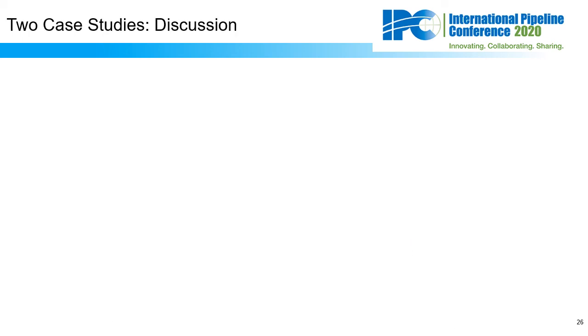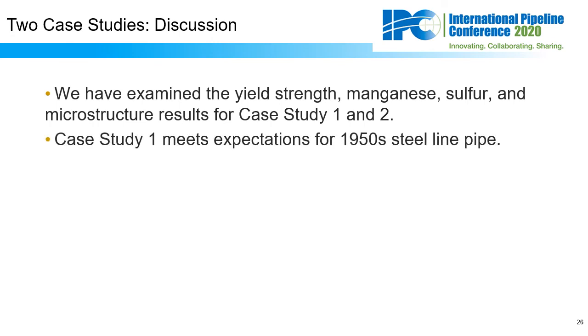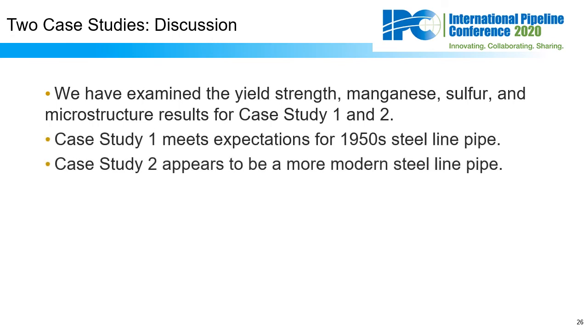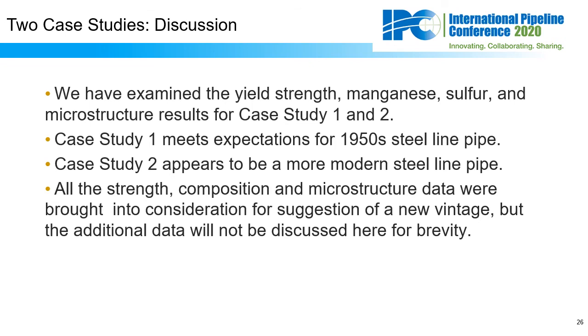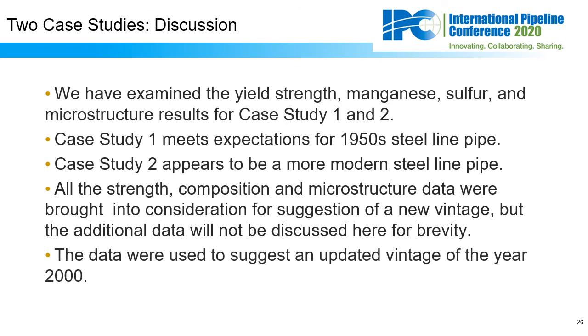So now that we've looked at the yield strength, manganese, sulfur, and the microstructure, our next step is to suggest a vintage for case study 2. We've confirmed that case study 1 appears to be representative of a 1950s steel, but case study 2 appears to be more modern. More composition data was considered in the paper associated with the presentation, but we can't cover all of it right now. So to suggest a vintage for case study 2, the data were prioritized and aligned with the most likely vintage from the historical trends that also found agreement with the microstructural observations. And this method was used to suggest an updated vintage of the year 2000 for case study 2.